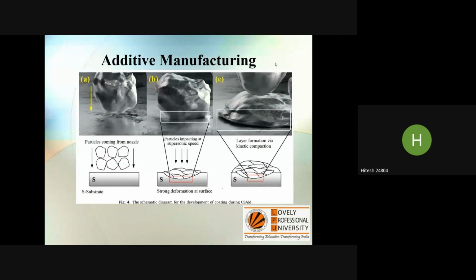Because I am talking about cold spray additive manufacturing, which is directly linked with the thermal spray, here we use powders as a feedstock material. Like here you can see in the first figure A, the particle is coming out of the nozzle. Because when we have to spray any material on some surface, we require high velocity, and for high velocity we have to use a nozzle. So that is why we have mentioned the nozzle.